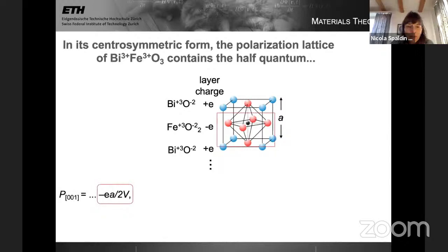And let me just quickly demonstrate that. If I'm calculating the polarization in the 001 direction, and if I take this to be my unit cell, and these atoms to be my basis, then the positive layer from the bismuth 3 plus oxygen 2 minus is at 0, and the negative layer, which has charge minus e, is halfway along the unit cell. So my polarization, the dipole per unit volume, is minus e times a over 2V. If instead I choose my unit cell like this, then my negative layer is at 0 and my positive layer is halfway up the unit cell.